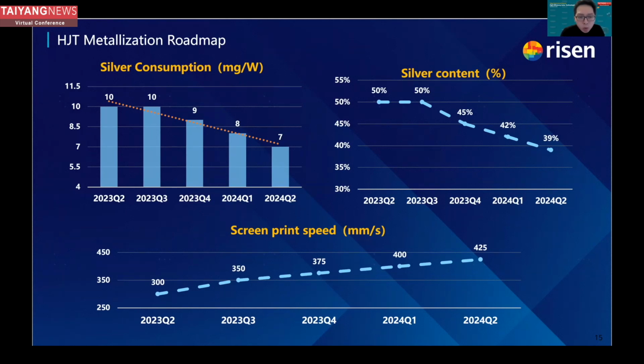And in the next step, we will further reduce the cost of silver consumption, reducing the silver content lower than 45% in this Q4, and next year we'll be reducing further to 40% or lower. Thus, the silver consumption will be reduced from 9 mg/W to 8-7 in the next years. And all along, we also accelerated the screen printing speed for the heterojunction cells, which is part of the ramping up of heterojunction mass production.